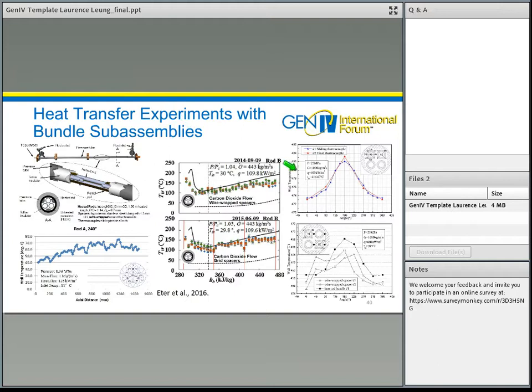We have done the 4-rod bundle in high pressure water flow. The flow condition is 25 MPa, 1,000 kilograms per meter squared per second flow, and the temperature at 416 degrees Celsius. The rods themselves are equipped with a movable thermocouple in one rod and a fixed thermocouple in the other rod. And these are the data without any spacer effect.